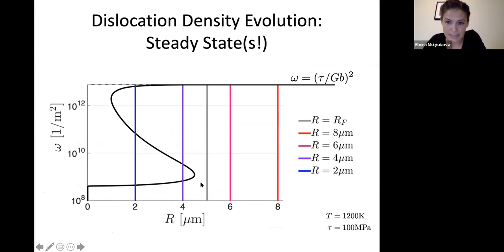Again, the grain line is the field boundary. These two lines are grain sizes that are larger than the field boundary. As you can see, the only steady state dislocation density they have available is this value that is the same as what is experimentally predicted and predicted by some other theoretical models of steady state dislocations. However, once your grain size falls below a certain size, that certain size being the field boundary, for example, there's a possibility for another steady state.